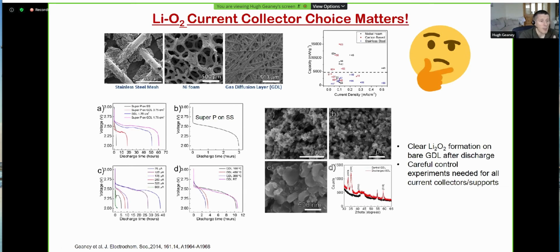So the testing that we did is probably the most rudimentary testing that we ever had to do in terms of delivering a paper. But what we did was we did discharge tests on the various current collectors, with focus on the gas diffusion layer in particular. So this is a carbon-based system. And what we found out was that, obviously enough, lithium peroxide was forming on the current collector. So when people were going back and calculating capacities for active materials that they had placed solely on the current collector while neglecting the mass of the current collector, they were drastically over-reporting their values.